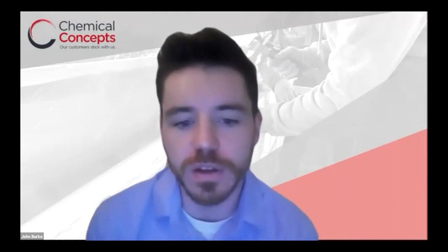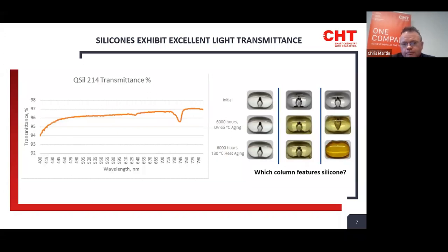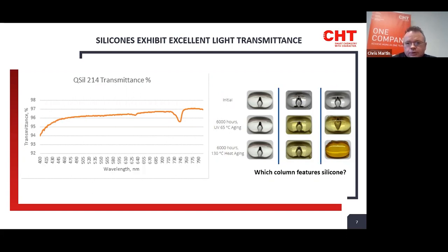Another question: will the silicone's color shift LEDs? When you apply a liquid to an LED, yes, you're going to have some color shift. With silicones, generally, that shift will be less than other organic chemistries, but there will be a shift. It varies from LED manufacturer to manufacturer, so it will require some evaluation on your part. However, silicones will shift it less than other chemistries. And the other benefit is that as the chemistry ages, it doesn't discolor — it maintains that same clarity compared to an epoxy. So whatever color shift you get when you first produce it, that's essentially the color shift you can expect years down the line.